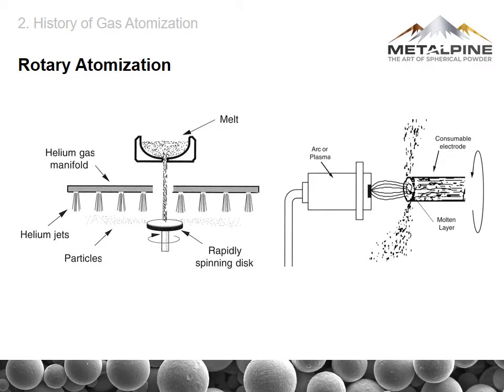Rotary atomization is a means to produce spherical powders with a narrow particle size distribution. You can see here the melt falling through a hole onto a rapidly spinning disk. Due to centrifugal forces, the melt forms a melt sheet on the disk, and at the edge of the disk it is divided into fine particles. They are rather spherical, but as the relative velocity between the sheet and the surrounding air is low, the particle size you would expect from this is rather coarse. There are not really fine particles usable, for example, for binder jetting or for additive manufacturing via powder bed fusion.